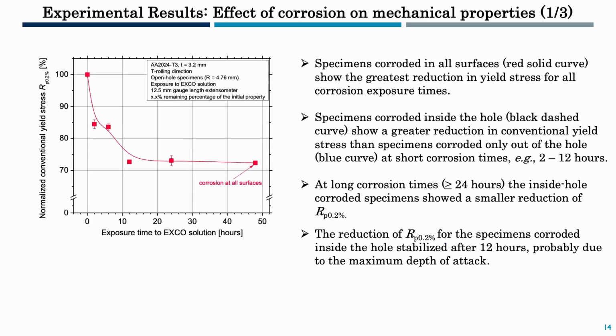The analysis of these results, the results of tensile tests, starts with the presentation of the normalized values of the average values of conventional yield stress with regard to exposure time to EXCO solution. And it is evident that specimens corroded at all surfaces, represented by the red curve, saw the greatest reduction in conventional yield stress for the whole corrosion exposure time. While specimens corroded only inside the hole, represented by the black curve, saw a greater reduction of the conventional yield stress for short exposure times and up to 12 hours. And at long corrosion exposure times, more than 24 hours, the inside hole corroded specimens showed a slightly smaller reduction.